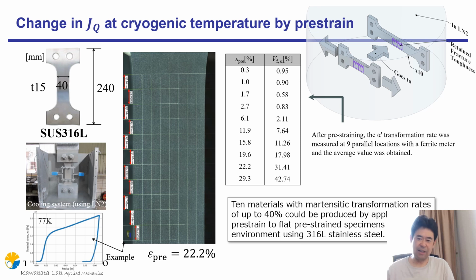This is the J integral critical fracture toughness. We assume a huge earthquake causes a large amount of plastic strain in some tank design through buckling. Toughness degradation due to plastic deformation is a major concern. This slide shows pre-straining at 77K using plate type specimen like this. From the uniformly pre-strained tensile specimen, CT specimens were cut and tested at cryogenic temperature.